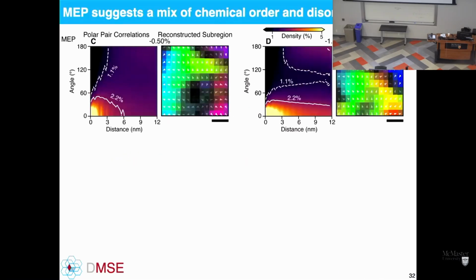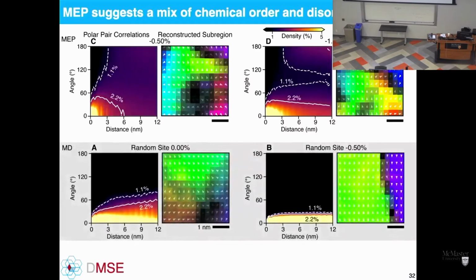Now, that's important because we can do the same thing from ptychography as we can do from molecular dynamics calculations. And if we try and compare these molecular dynamics calculations, this is a local, it's a random site occupation of an ordered lattice, essentially, of the magnesium, niobium, and titanium. But the important thing is there's chemical order in this case. And what you see is something very different from what we see experimentally. So these would say theory isn't right.